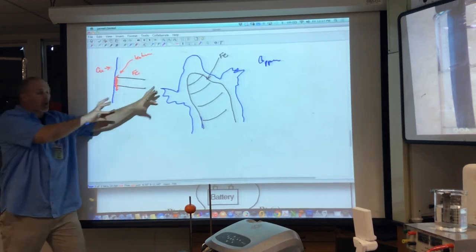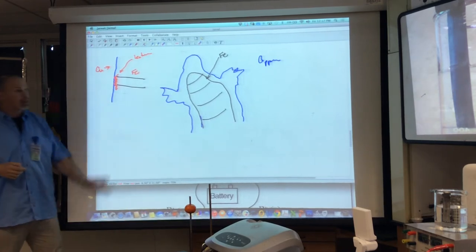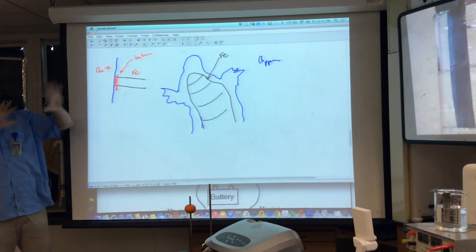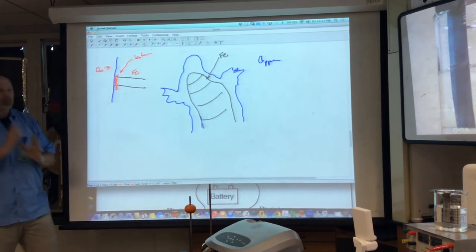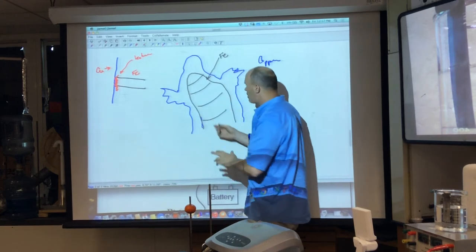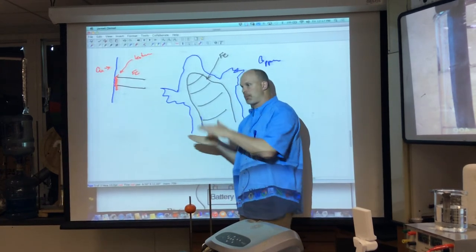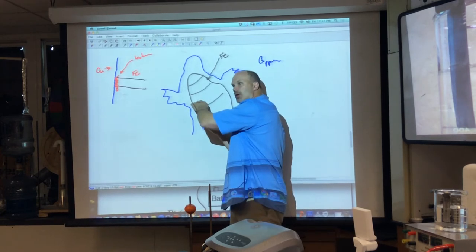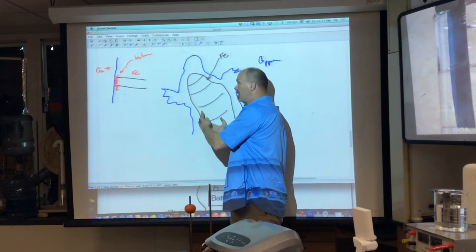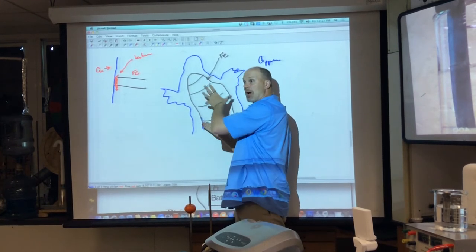So they had to take off the copper sheets, replace the iron, and then put it back, but instead of putting this little layer here to protect it, they made it a plastic layer. They also created little spots where they put little pieces of sacrificial anodes, little magnesium bars, against that iron. So that makes the magnesium the anode, sacrifices the magnesium, and prevents the iron, now the cathode, from oxidizing.